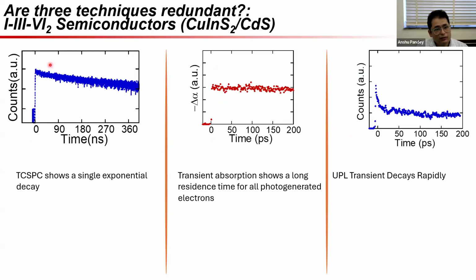So what happens here? Well, the first thing you see is, okay, you get a TCSPC, and when you do TCSPC, you get a very nice clean exponential, which is great. This again seems like a very, very boring material, perhaps not something one might want to look at in great detail, especially because it's a very similar exponential, which makes it in some sense more boring. Nothing interesting is happening. If we look at this material's transient absorption, we find something similar.